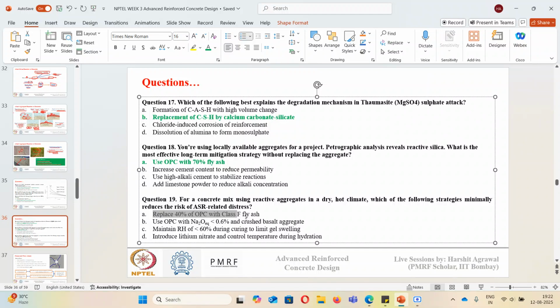If you see, using OPC with fly ash will densify the pores, and it will reduce the risk of alkali silica reaction. If we have OPC with low alkali content, then again we can reduce the risk of alkali silica reaction. And sometimes introducing lithium nitrate also helps in reducing the chances of alkali silica reaction in the system. Okay, the one thing that will least contribute is the control of RH.